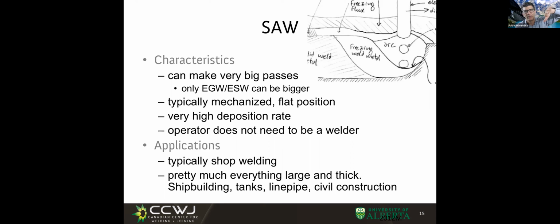If it is small, surface tension can be okay. It's the case of MIG or the case of flux core. But if the weld starts to be very big, as we mean it to be in subarc welding, it's going to sag, it's going to roll down. So subarc welding, flat.